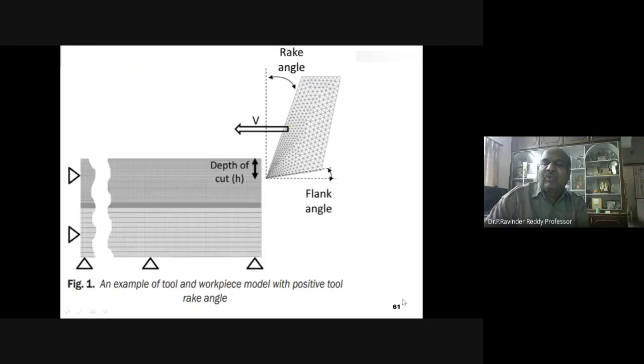So when you increase the speed, definitely you know that the temperature is increasing, and you can see the temperature variation: when the speed is 9.8 meter per minute, it's 165 degrees centigrade, and at 50 meter per minute, it is increasing to 285. When you showcase the same in fundamental modeling, so here the damage mechanics, earlier I've shown steady state heat transfer. When you want damage mechanics, we need to have a contact location for this and a very fine mesh. And when you have a tool, you can also see the tool. We have very high mesh density because the chip and tool are going to have contact. And this tool is now moving along the radial direction.